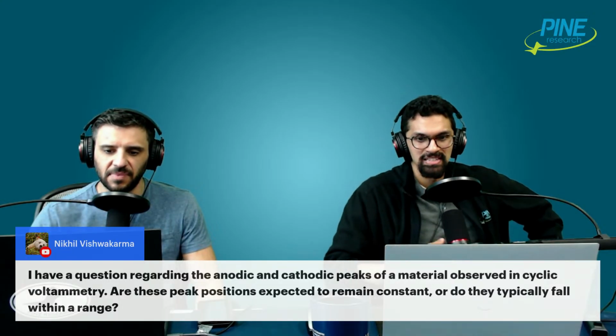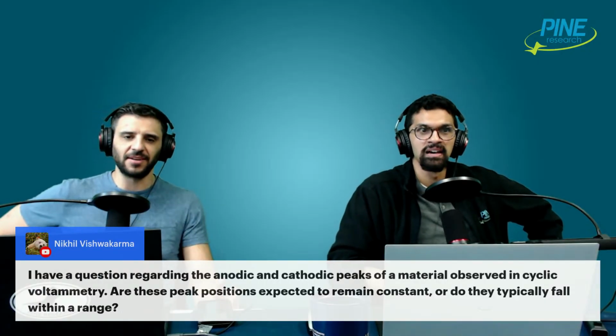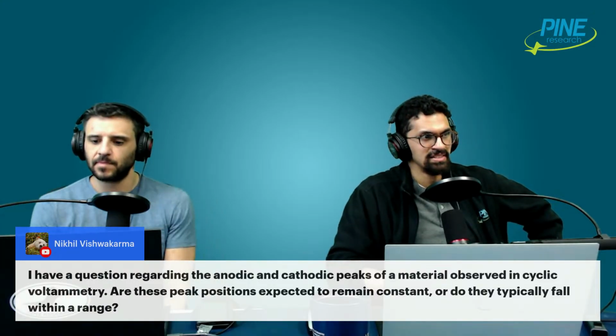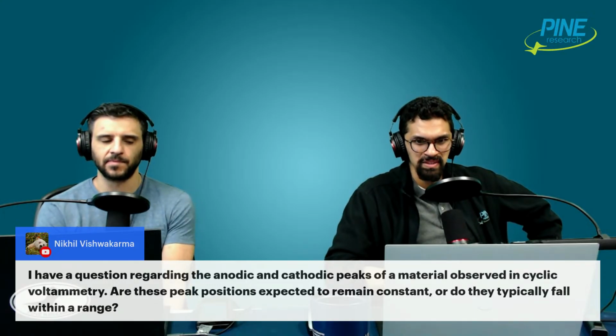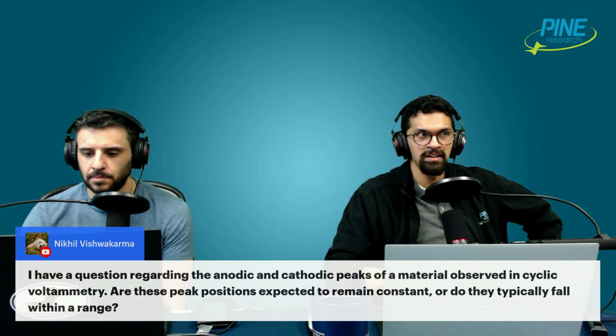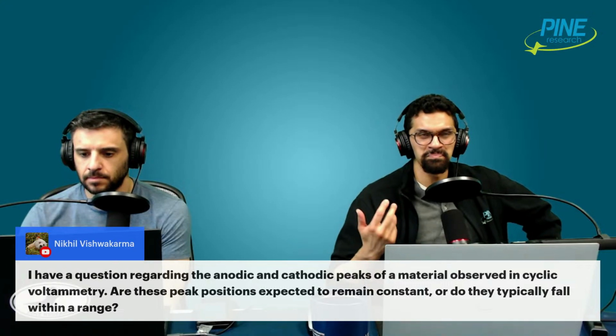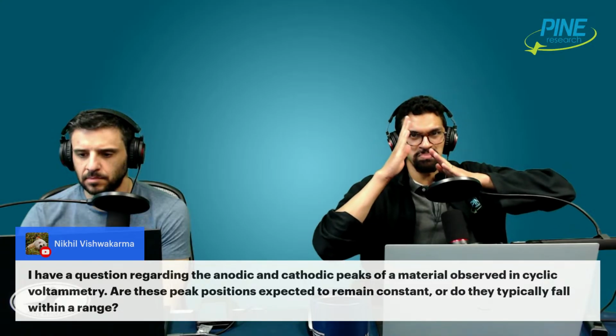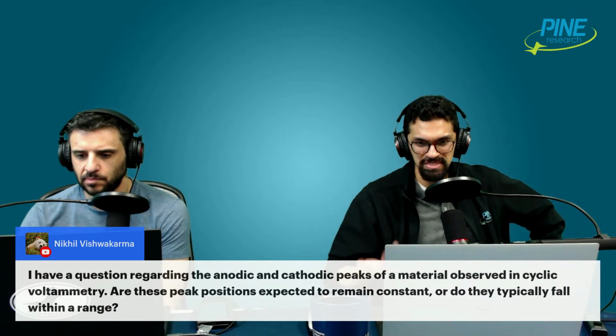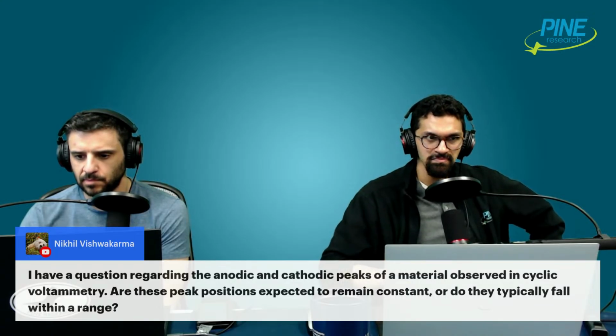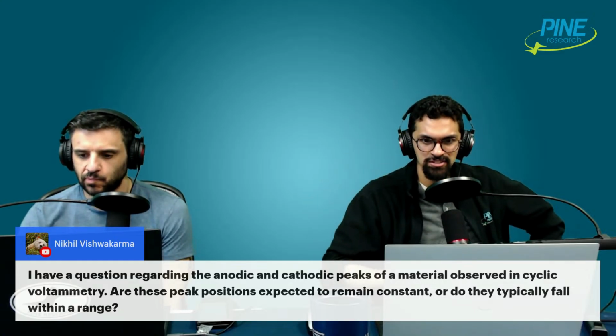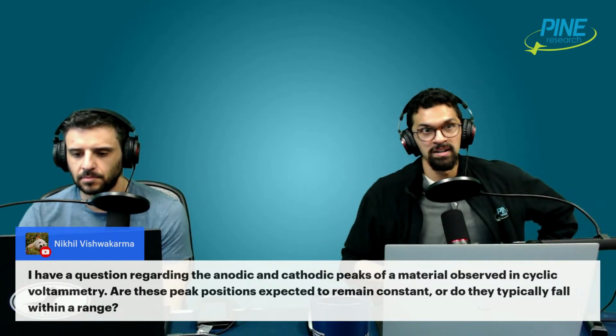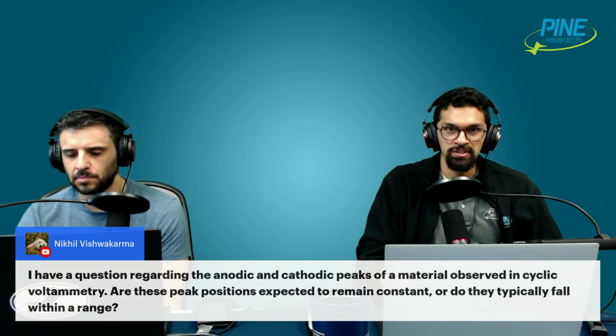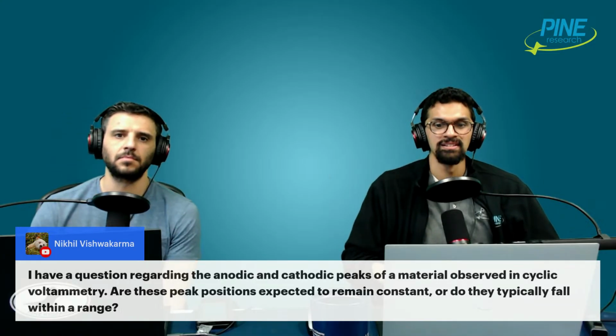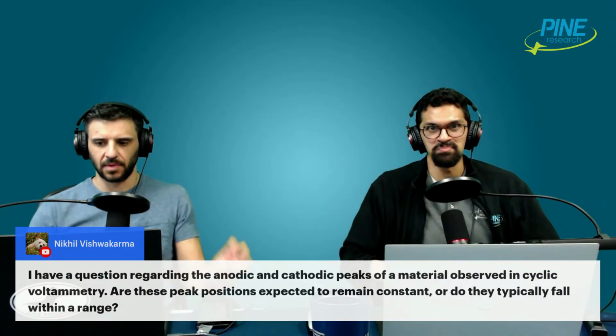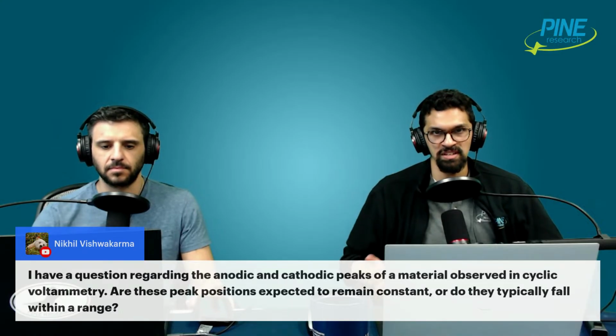So it's interesting. It depends. Theoretically they shouldn't change. But oftentimes in different chemical systems, a lot of things can happen. As you cycle, you may get things like increased IR drop, or some junk gets on your electrode surface, and the peak splitting starts to increase because of solution resistance. Basically, you have a resistive element in your system. And theoretically, the positions of the anodic and the cathodic peak should remain the same if it's perfectly reversible, does not contain an IR contribution, and also doesn't deviate due to a chemical reaction or have a pH dependence. In that case, yes, they should be in the same position. But if there's drift in your reference electrode, that's another thing that can cause problems.